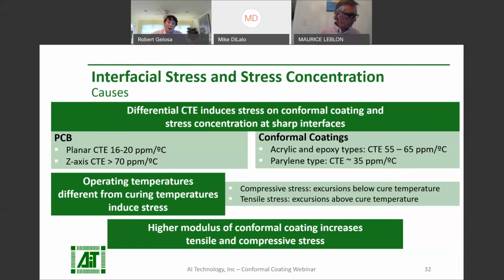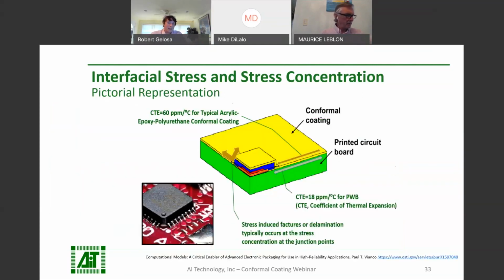With temperatures above curing temperature, tensile stress will be induced. This can cause cracking or delamination of the coating, rendering it useless no matter how much protection it supposedly provides. And naturally, the stiffer the coating, the greater the stress will be. In some cases, thousands of PSI are induced in stress. Stress concentration points usually occur at sharp interfaces.